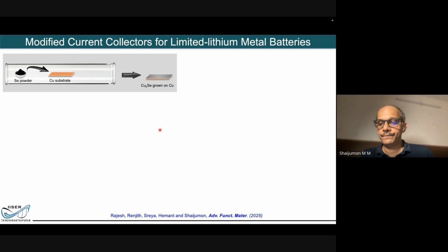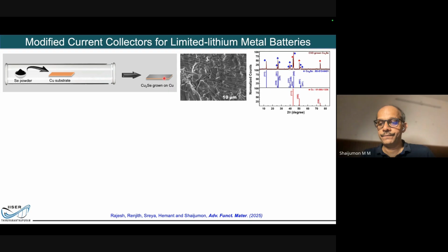So please understand this. From here onwards, my motivation is to come up with a very thin anode. It can be a very thin lithium onto my copper, for which I'm taking some steps. In this effort, done by my PhD student Rajesh, who led this work, he started with a copper foil. Using chemical vapor transport, he takes selenium, and that selenium is transported onto this copper, and you get a copper selenide, which means the top portion of the copper reacts with selenium to form a copper selenide on top. You do all sorts of characterization using XRD, scanning electron micrographs, all kinds of things. It's a very flexible film. You can see that, very flexible.